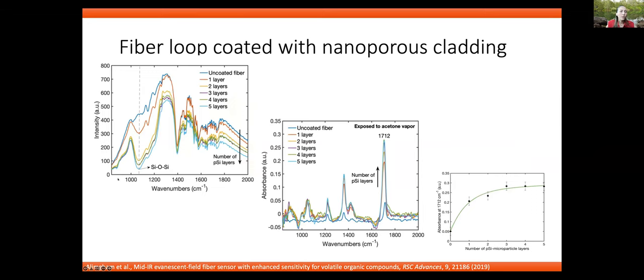So first thing we needed to make sure is that our nanopores don't completely absorb all light that's passing through the fiber. So for an uncoated fiber, you can see here intensity versus wavelengths or wave number. And it shows that we have these types of behavior, those peaks, and this is because the fiber absorbs something. This is also the light lamp that is used in the FTIR. It has a certain shape. But as we're adding more and more layers, we can see most of the spectrum, the absorbance changes only a bit. It absorbs a bit, but here we have a very strong absorbance.